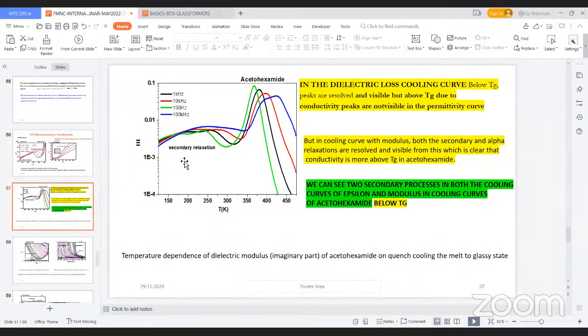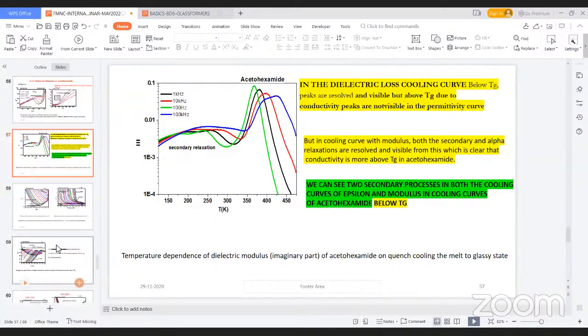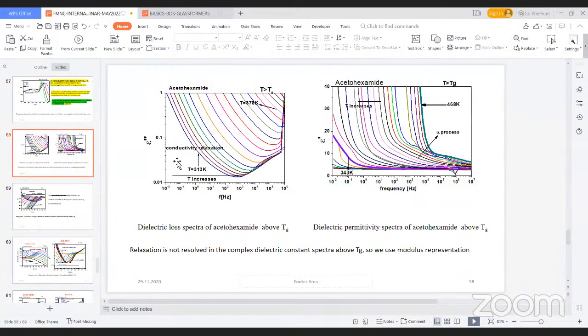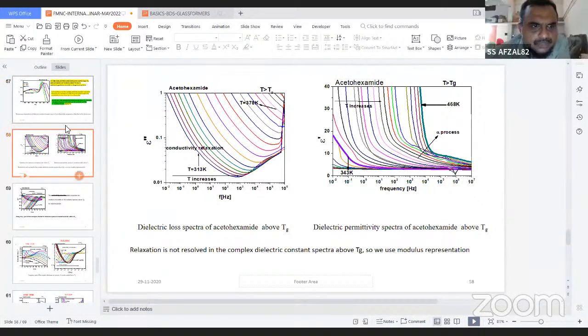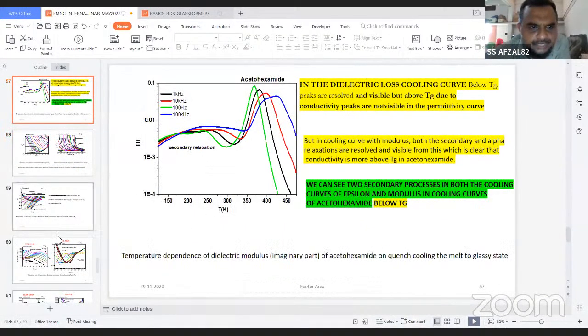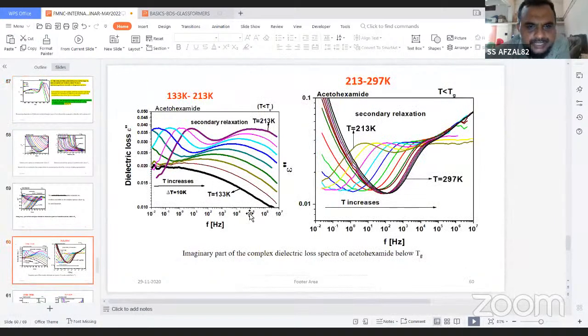But if I use the modulus representation, which is the reciprocal of the dielectric constant, I am getting the peaks corresponding to the conductivity relaxation or the dipolar relaxation. Similarly, we can plot the frequency spectrum. What you are seeing now is the temperature spectrum, that is, the x-axis is temperature. But here you can see the frequency on the x-axis, and the dielectric constant and the dielectric loss, which is the imaginary part, on the y-axis. And you can see here, in the glassy state, I am getting peaks corresponding to the secondary relaxation. And this is also the dielectric loss at a higher temperature, that is still in the glassy state.